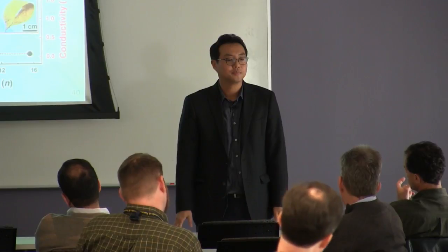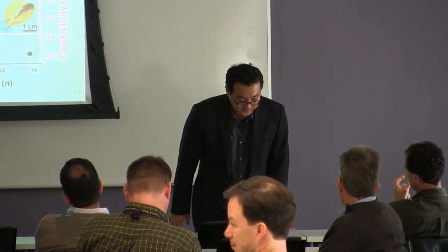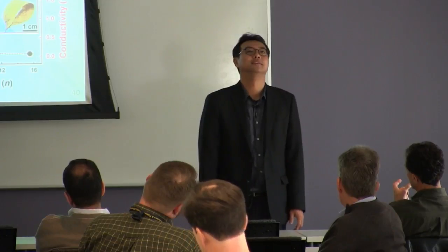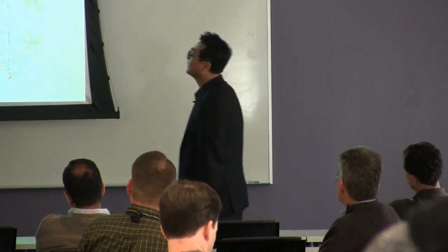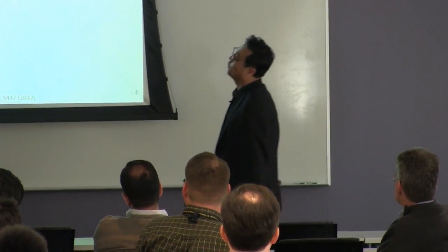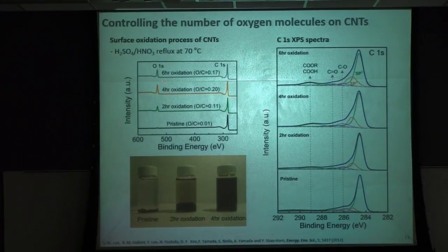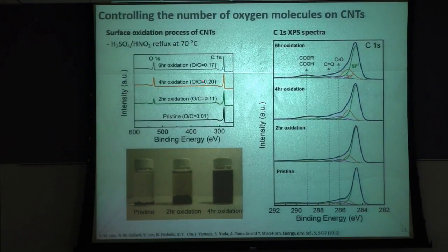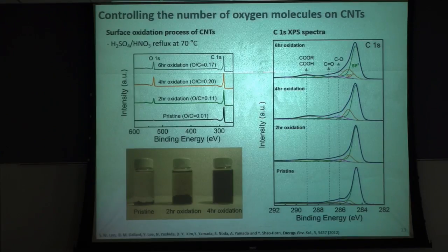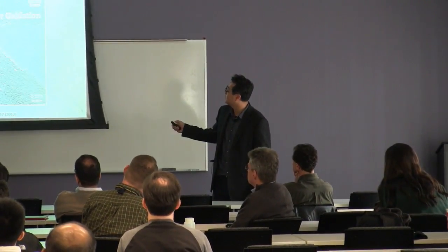When you talked about the surface roughening of the carbon nanotubes, is there any negative effect on mechanical performance, as you worry about, let's say, in lithium-ion batteries because of that? Actually, there is, but there is an optimum oxidation time. For example, let's see here. Pristine, 2 hour, 4 hour, you can see a gradual increase of the oxygen to carbon ratio. Eventually, after 6 hours, something happened: there is cutting of these carbon nanotubes. They mechanically degrade because of too much oxidation. It's the maximum oxidation time. As you can see, this roughened, eventually the oxidation radical cuts these nanotubes.